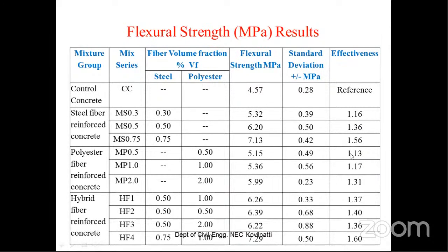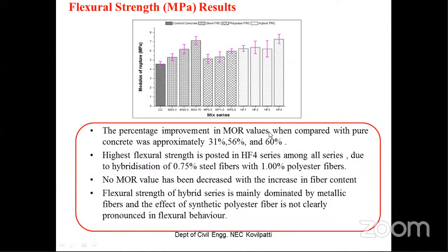Flexural strength improvement is somewhat lower than the split tensile strength improvement, but it is not a big drop. In steel fiber reinforced concrete, the improvement is between 16 to 56%. For polyester, I observed between 13 to 31% improvement with increase in fiber content. And in hybrid fiber reinforced concrete, the improvement is in the range of 36 to 60%. So the MOR values improved approximately 31 to 60%. Among them, the HF4 series, which contains more steel fibers and more polyester fibers, shows the highest flexural strength. No MOR value has decreased with the increase in fiber content.